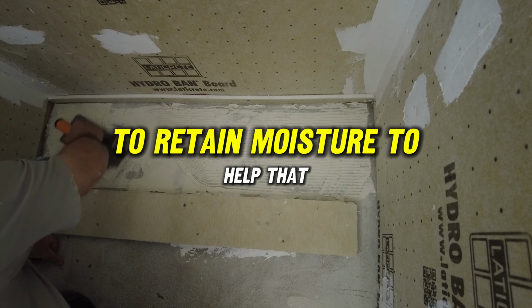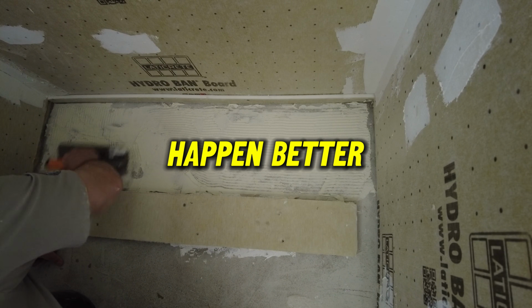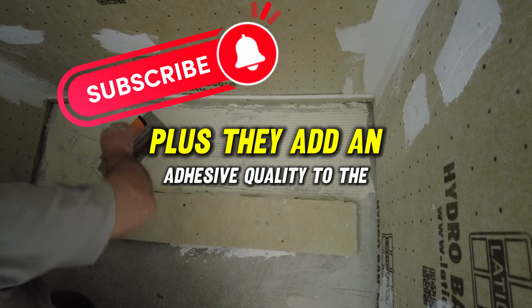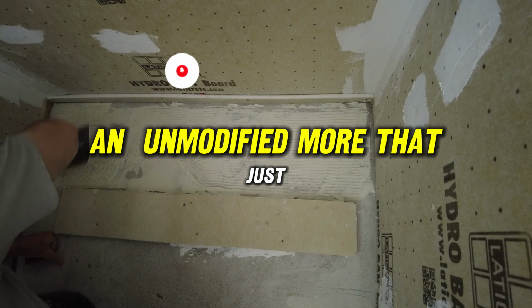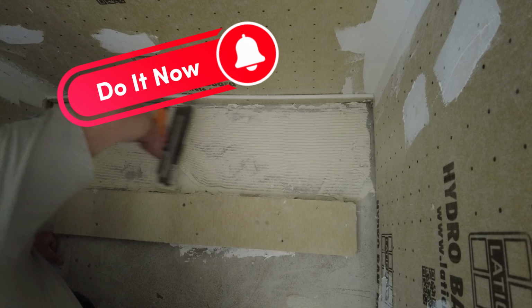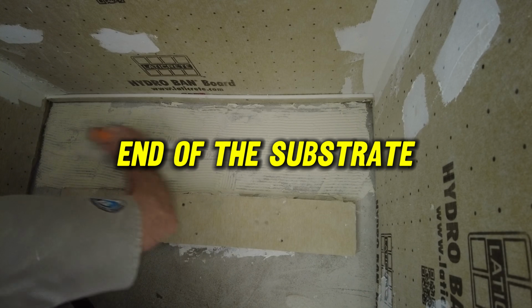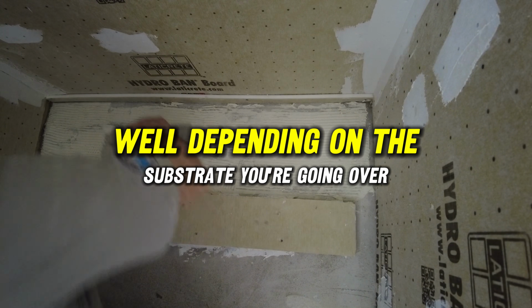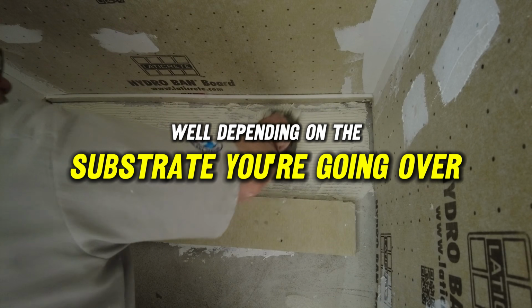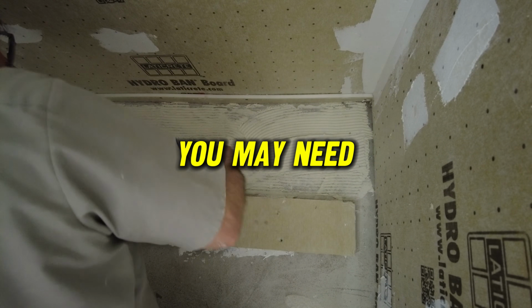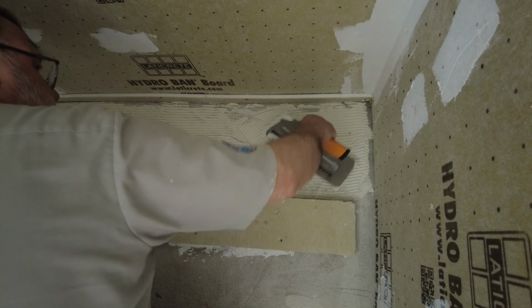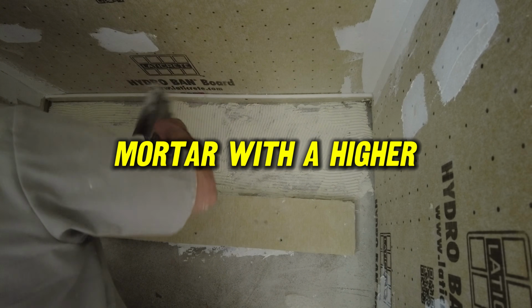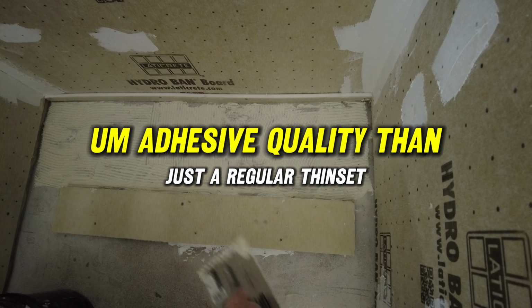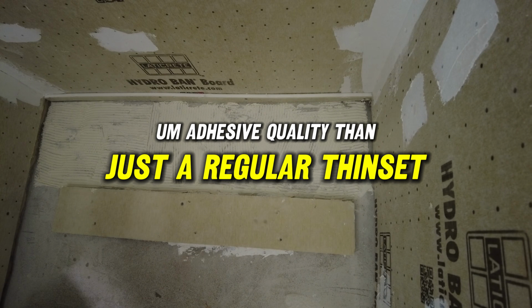The polymer modified thinsets are designed to retain moisture to help that happen better. Plus they add an adhesive quality to the thinset. An unmodified mortar only depends on the crystals growing to penetrate into the substrate. So why does that make a difference? Well, depending on the substrate you're going over and the tile you're going over, you may need a mortar with a higher adhesive quality than just a regular thinset mortar.